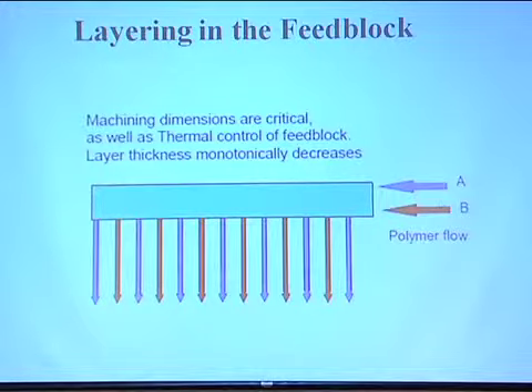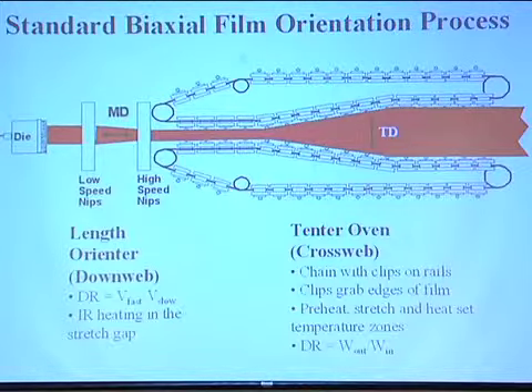This cartoon shows the manifold where two polymers go into two different manifolds side by side, and then out of each manifold come hundreds of layers that come together alternating. And then we also have a machine here for orienting the film. Sometimes there's two steps. We stretch the film in the machine direction to give it birefringence that way, and then we stretch it in the transverse direction to give it orientation that way. Again, that gives the film thinness, it increases the modulus, gives it strength, and greatly increases the refractive index to give it the optical power we need for reflecting light.